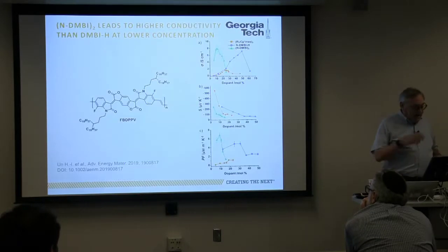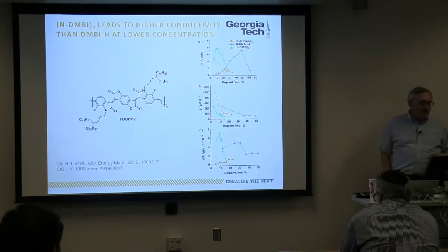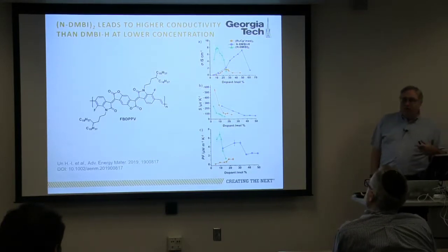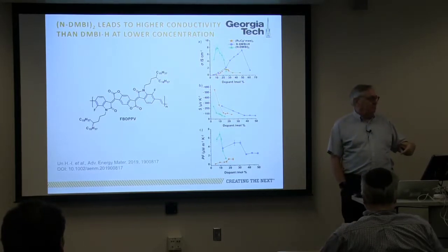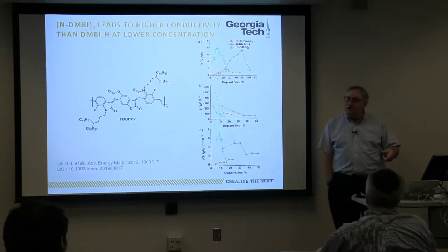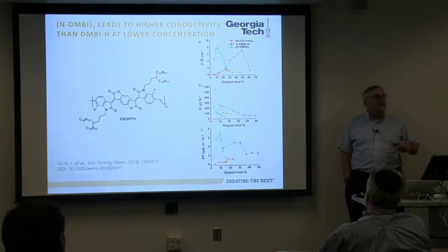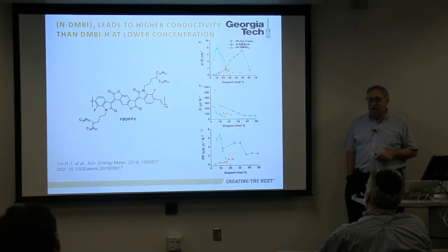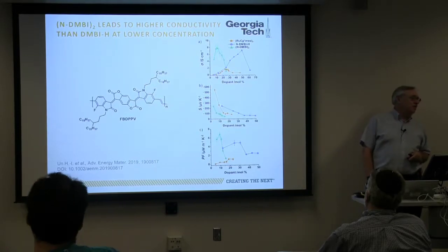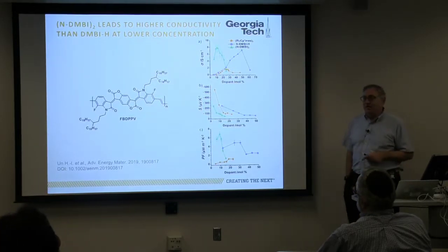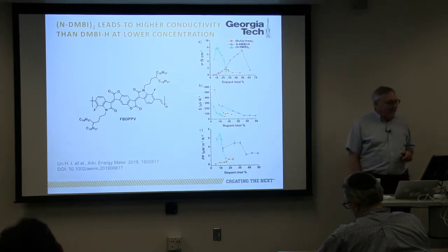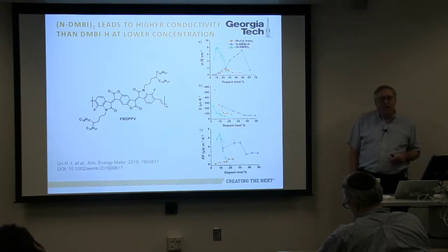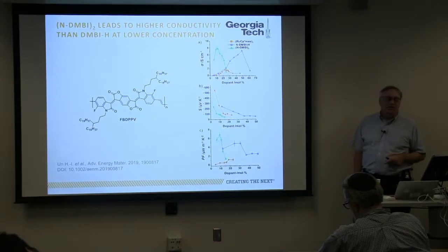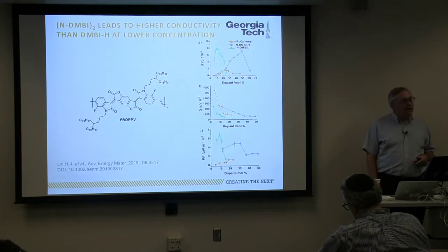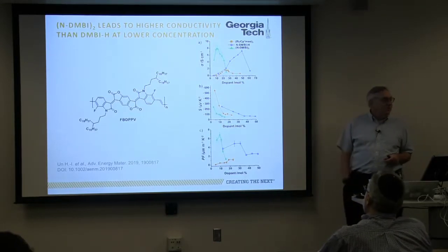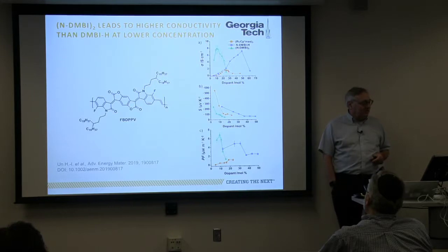Okay. Another example, which is of maybe less interest to this audience, is that of n-doping a polymer. So there are many p-doped polymers, and the p-doped polymers, as I've noted, can give rise to conductivities quasi-routinely as high as 1,000 Siemens per centimeter, and in some recent cases, as high as 10 to the 5 Siemens per centimeter. For n-doped materials, if you get 10 to the minus 3 Siemens per centimeter, you're not surprised. You consider that okay. If you get 10 to the minus 1, you're feeling good. If you get 1 Siemens per centimeter, you're feeling very good. Okay?